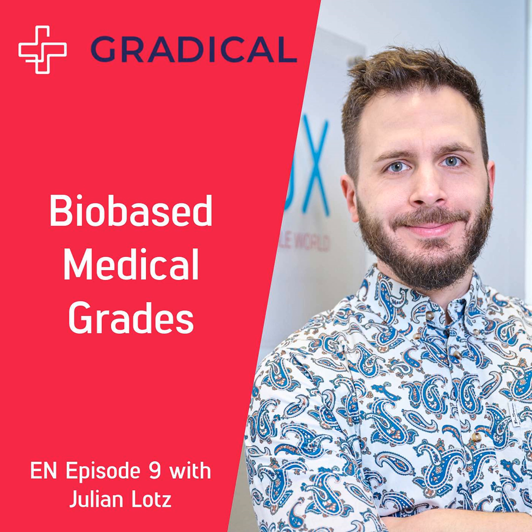The thing with accelerated aging is always that people actually don't know what they're doing there. Because accelerated aging is like you bring it up to a certain temperature in the assumption that you are in the same domain of the chemical processes that take place with the same reaction taking place. So there's no other reactions going on there. And what you usually do, or what the recommendation is, is to stay below Tg. And if you're close to the glass transition temperature, you basically get other processes involved.